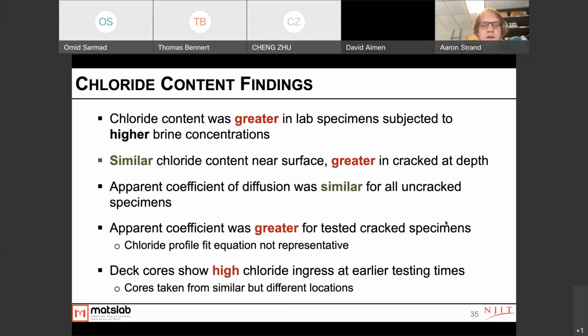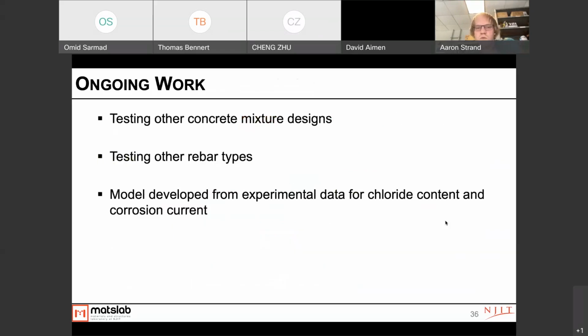And then the apparent coefficient was greater for all tested cracked specimens, and again, this makes sense as the chlorides can penetrate much quicker. But again, this chloride profile fit shows that this might not actually be representative of what's actually occurring. And then the chlorides show high chloride ingress at very early testing times, and again, the cores are taken from similar but different locations.